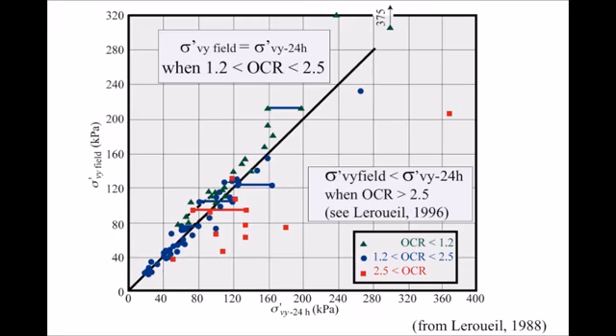About the first question, in fact, we compared sigma prime Vy in the field with sigma prime Vy obtained after 24 hours, and we obtained a good agreement for OCRs lower than 2.5. For OCRs larger than 2.5, the field data are smaller, and this has been explained by the shape of the limit state curves of natural clays.